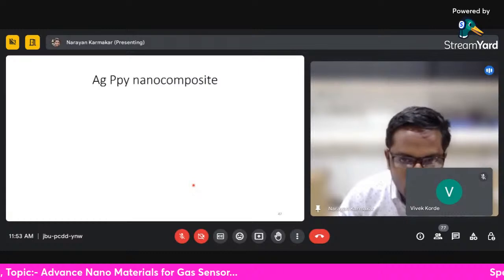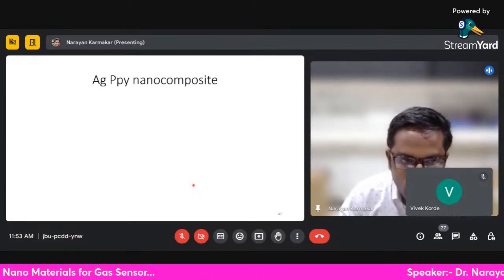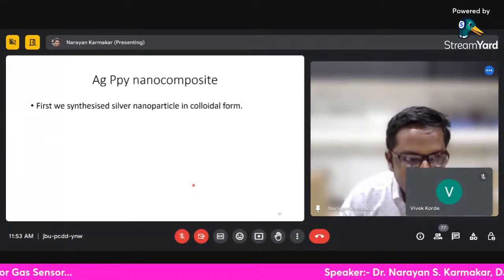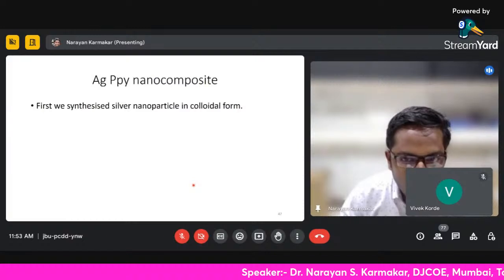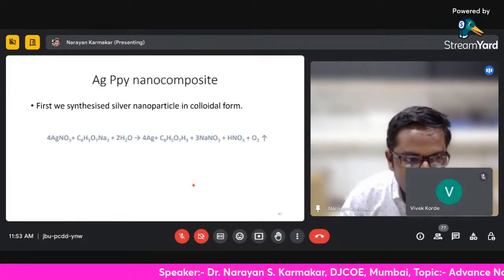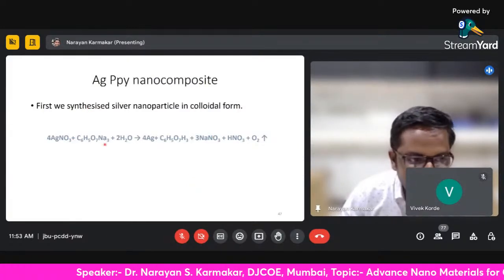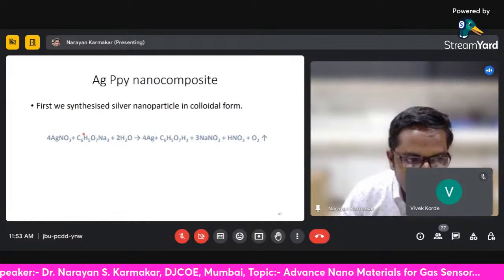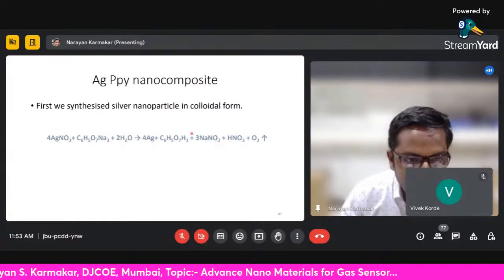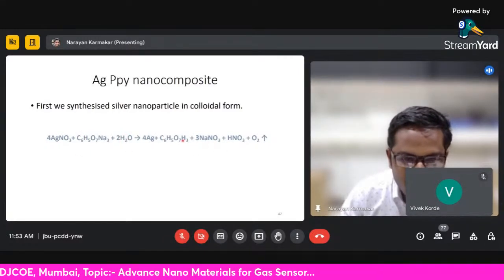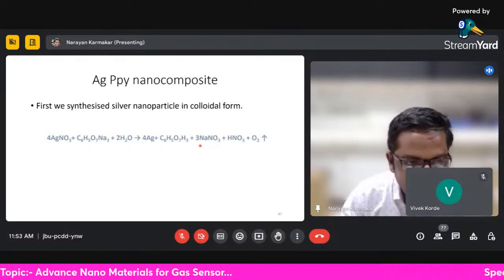So first, how do you synthesize this AgPPy nanocomposite? What you do is this: you synthesize the silver nanoparticle in the colloidal form. This is the reaction mechanism where we make use of silver nitrate and trisodium citrate to synthesize the silver nanoparticle, which is mainly in the colloidal form.